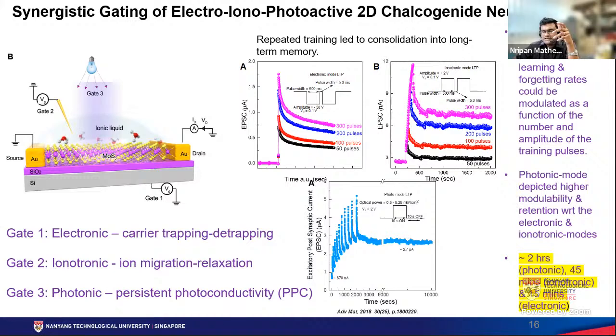And that's an interplay, because when you excite charge carriers over here, the carriers can get trapped at the interface and continue to stay on the channel due to the ions accumulating on top of the channel, etc. So there are multiple intercouplings that can be done. And the fact that it is a 2D material is also helpful because it's an ultrathin channel, so you have very good control over the carriers in the system. Showing these optical effects can actually increase and control the synaptic characteristics.